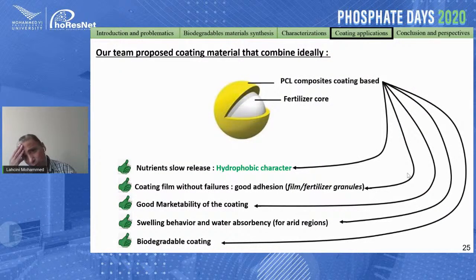For that, we chose to use our PCL nanocomposite that we prepared first, because we can control the hydrophobic character. That guarantees the slow release. We have good mechanical properties. We will not have failures. It's easy to prepare the polymer. I guess there is good marketability of these coating materials. We can increase or decrease the filler contents to tune the swelling behavior, and also our nanocomposite is biodegradable, as the filler and the polymer are biodegradable.